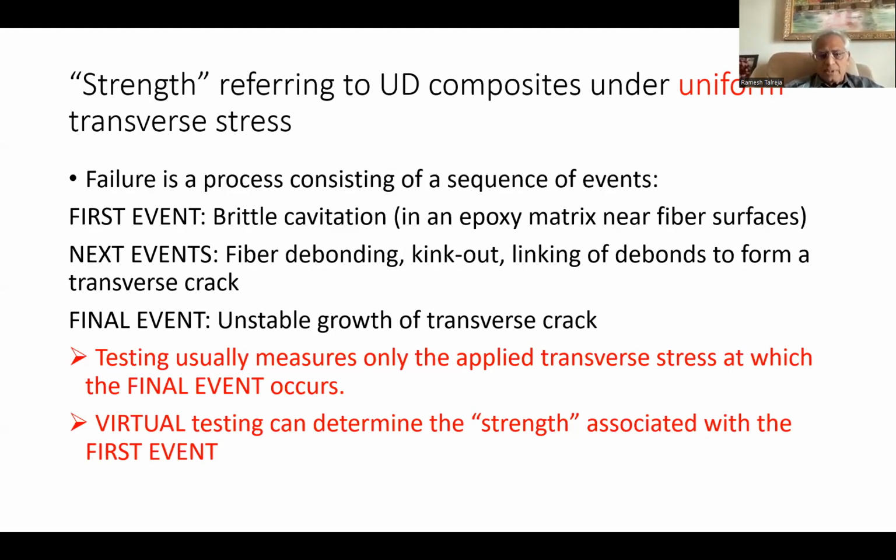And depending upon the material, they are going to be differentiated differently. So if we focus on epoxy or glassy polymers generally, then the first event under applied uniform tension normal to the fibers has been now quite well established, beginning with Leif's work back in 1995 or so, that brittle cavitation is the lowest energy requiring mechanism, and it occurs close to the fiber surface when you have multiple fibers, not a single fiber.